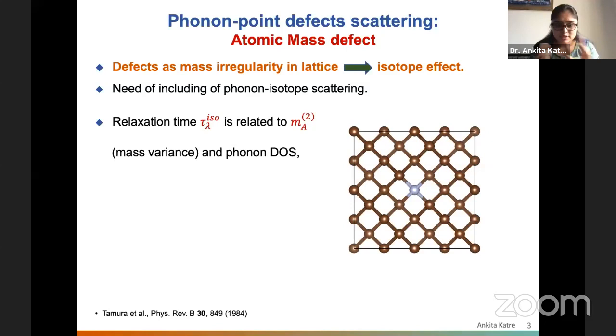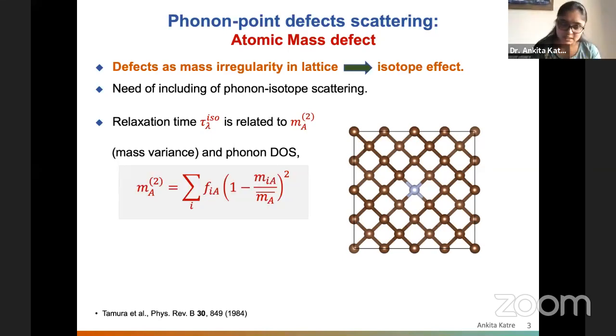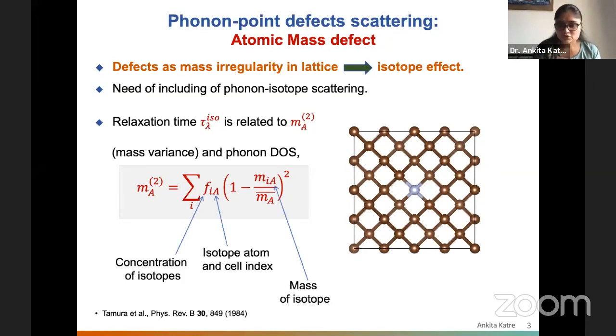And to broadly explain what main ingredients it needs for the calculation of this scattering rate, it relates to the phonon density of states of the unperturbed system, and to incorporate the effect of defects, we need the mass variance of the defect, because it's just a mass defect. The mass variance is summed up in this formulation here. It depends on the mass of the isotope as well as the concentration of the isotope. I are the number of isotopes for that particular species, A is the atom index, which atom we are actually working with, F is the concentration, and M is the mass of that isotope. The total effect is calculated by summing over all the isotopes of that particular species.